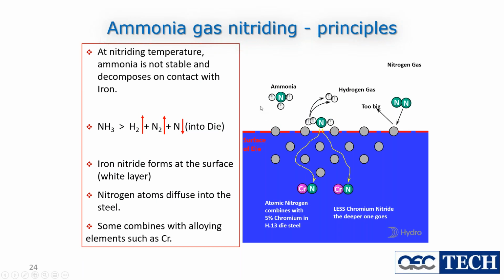So here's a little bit of a schematic of what we're looking at. Ammonia, NH3, with the right balance of nitrogen and hydrogen, because this is a dissociation reaction. So if we bump up the amount of hydrogen and nitrogen gas that's in there, we slow down the dissociation of the ammonia. So that's how we trick the system to run at the speed we want it to run at. And the product of this dissociation reaction is a nitrogen atom.